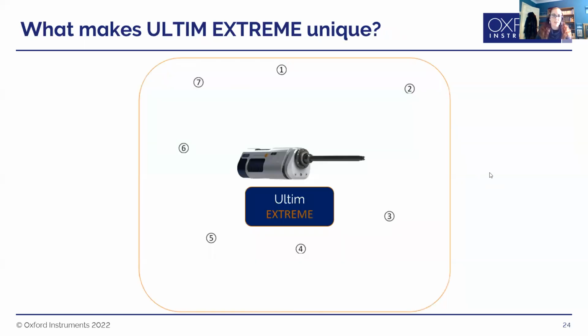So in order to overcome this, we developed the Ultim Extreme detector, and that's what we've got here. This involved several things. For example, we changed the electron trap. You can see the sensor inside the detector here, and this is what senses the X-rays. And you can see it's much closer to the snout of the detector than in a standard EDS system. That's because we modified the electron trap.